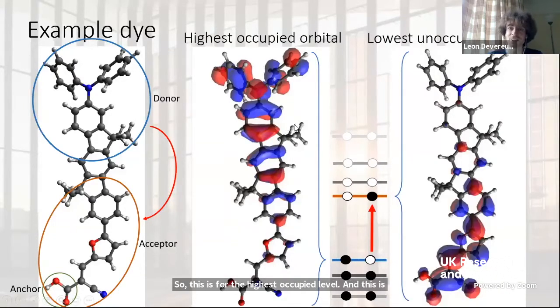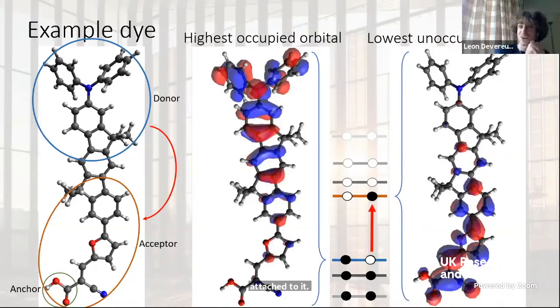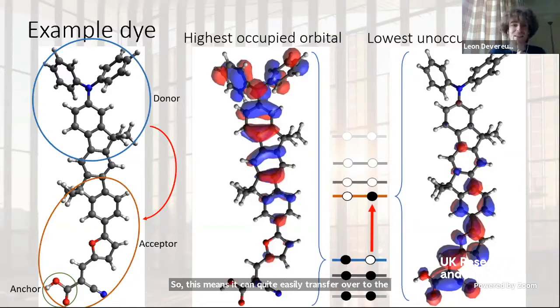So you can see at the top, it's mostly up here at the top of the dye, and on the right here, it's mostly down the bottom. And this is important because it's closer, once it's been excited, to the surface of the semiconductor it's attached to. So this means it can quite easily transfer over to the TiO2, this titanium dioxide. But then once it's been transferred, it's much harder to get back to the hole, which is left behind in the donor region.